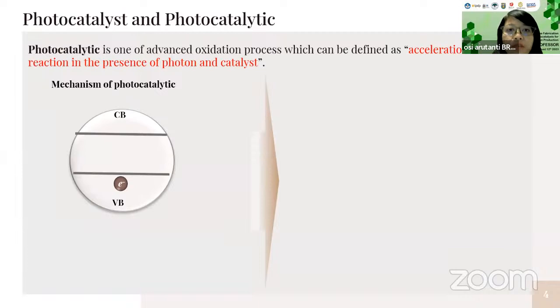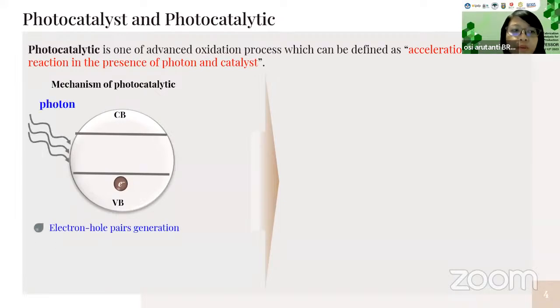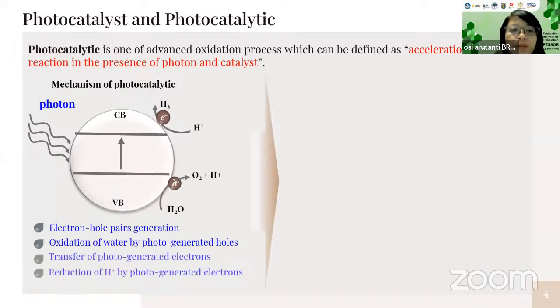Because we believe that this method is relatively cost effective and environmentally friendly, and also we can use solar energy to activate our catalyst. This is the mechanism of photocatalytic hydrogen production. Simply, when the catalyst absorbs a photon, pairs of electron and hole are produced, and then the generated holes in the valence band will oxidize water into O2 and H+, while the generated electrons in the conduction band will reduce the H+ into H2.